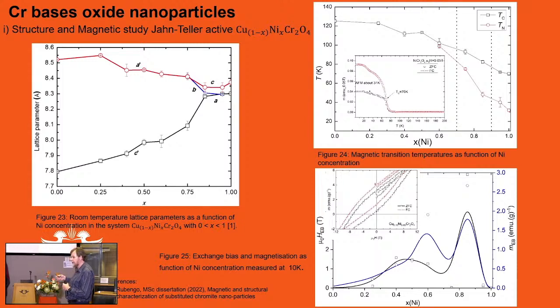And what that does, it actually compresses the octahedron, decreasing effectively the distance, increasing some of your interactions. So this here is just the lattice as we doped with the nickel. You can see it goes from cubic to a tetragonal phase in this case. And then, of course, we extracted, again, the transition temperatures. But the interesting bit is around about 50, 55, 60, you actually see two. You see a Curie temperature, and you see antiferromagnetism simultaneously.